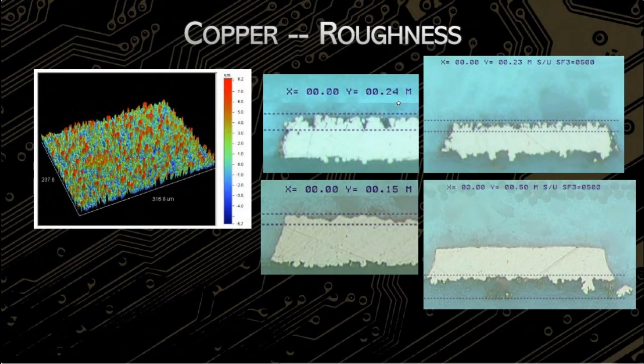Trouble with that is surface roughness increases the dissipation of your signal as it propagates along the lines. So if we look down here, you can see two parts of copper foil. I don't really know how this was made, but if I had to guess, I would suspect this. Well, actually, I'm not going to guess. But we've got one part of the foil that's very, very smooth and the other part that's very, very rough.